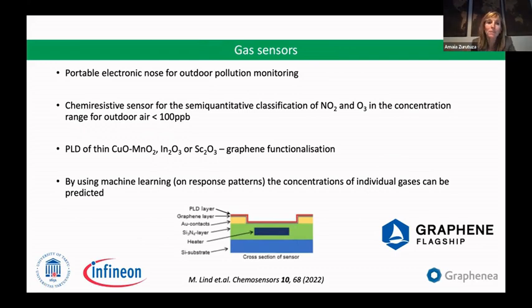They used pulsed laser deposition to deposit metal oxides on graphene to make them selective to NO2 or ozone. And then by applying machine learning on the response patterns, we could even predict the concentration of the individual gases. So it also shows quite great potential for gas sensors.